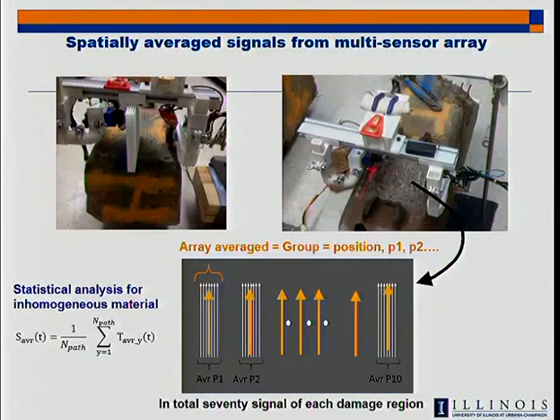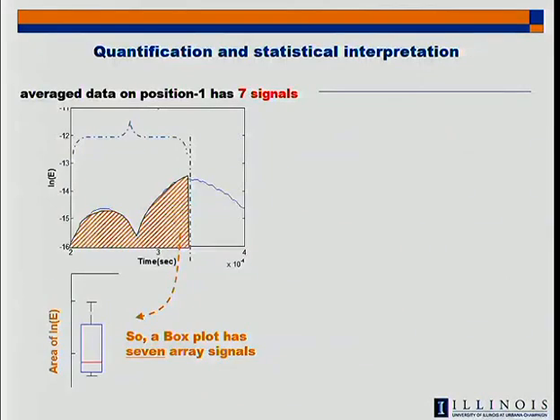Another question is, how repeatable are these data? We collect them along one scan across an RSD area, but are they consistent on this rough surface, and can we count on them to characterize, that is, a signal set? So what we did is we took 10 sets of signals, each one we repeated 7 times, just to see if we go back to the same thing, do we get about the same numbers? And if we go on different levels of RSD, do we see a distinction between the two?